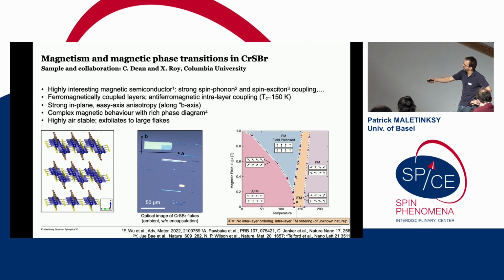So first off, what is the magnetic order? This is now an in-plane magnetized material where a given layer orders ferromagnetically, but adjacent layers show anti-ferromagnetic correlations with respect to each other. This material cleaves beautifully into very large flakes. You see an optical micrograph, so you get flake sizes of tens of microns, which again addresses this materials issue I mentioned before. And all of this is air stable. It's air stable down to the monolayer, as I'll show you later on with data.